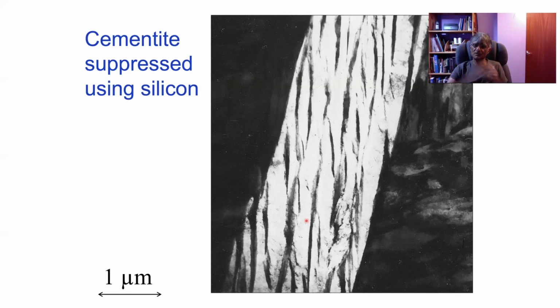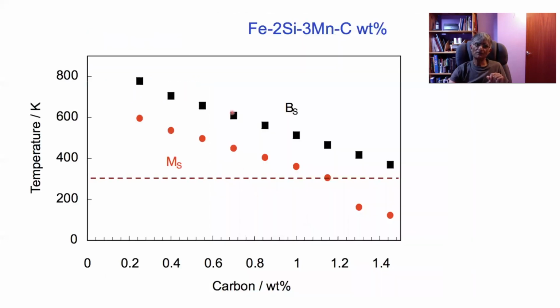So you can ask a fundamental question, what is the lowest temperature at which I can get bainite? Okay. And we can do those calculations. I haven't explained to you how to do that, but I explained to you how to do the martensite start temperature calculation using thermodynamics, etc. And we have the theory for the bainite reaction. And when we apply the theory, it's actually quite surprising that as long as you can keep the bainite and the martensite start temperatures separated, okay, you can suppress the bainite start temperature to room temperature. Okay, so you can actually form bainite at room temperature in this alloy and this sort of carbon concentration. Very surprising, okay? But there is nothing to say that this is wrong.